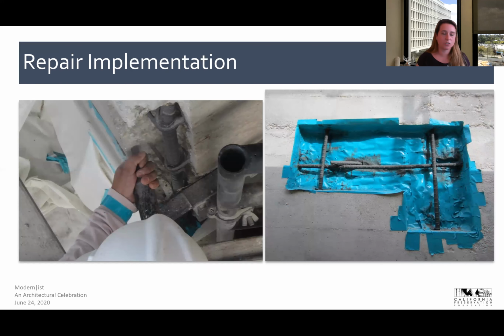Here you see a couple images of surface preparation ongoing. Again, surface preparation is critical to the success of any concrete repair, not just in a historic structure, but any concrete repair. Surface prep is really critical. You may be limited on a modernist structure or historic concrete structure to surface preparation methods available. Here you see a needle scaler being used on a structure, but that doesn't mean that surface prep could be less. A reduction in surface prep could lead to a reduction in service life of any repair. The photograph on the right shows the application of corrosion inhibiting coating, and that was really to mitigate corrosion, which was the primary deterioration mechanism as part of this project.